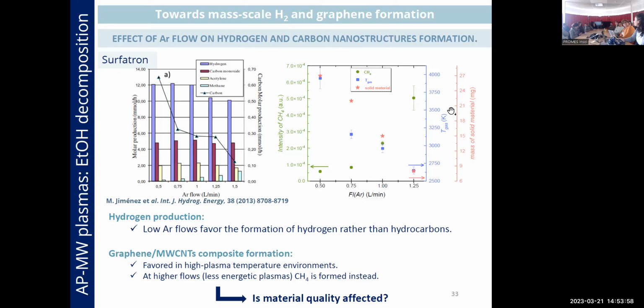What about gas temperature? You can see here in blue the values of our gas temperature, which decreases with argon flow. So what we have obtained, once again, is that as we have low values of gas temperature, the formation of solid material is limited because other light hydrocarbons are formed instead, for example, methane.